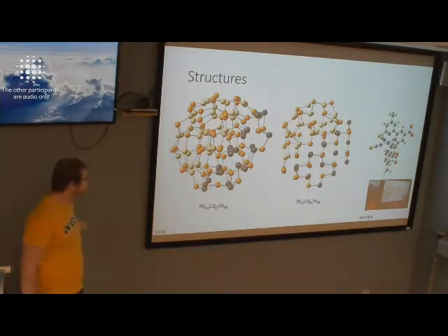I understand that. But my question is: you're saying you're not using the symmetric case, with the same number of lead and cadmium and a 1, 0, 0 facet, because in the literature they see more 1, 1, 1. But we still can compare which one is more stable. They have different numbers of different types of atoms, so you cannot just look at the total energy, but you can calculate the surface energy, the same as Navid was calculating for the nanoplates. If you look at the ionization energy, it's not useful.